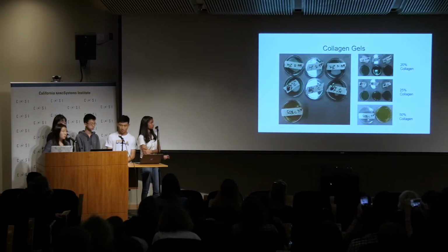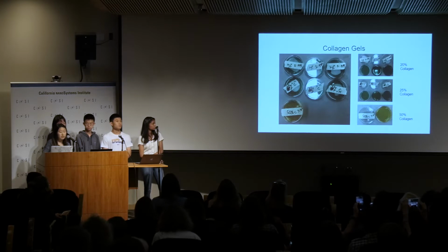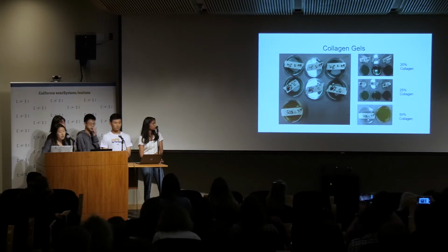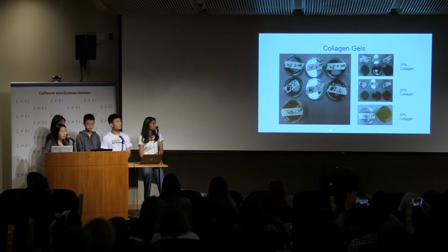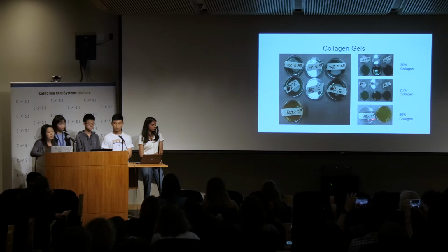So here are pictures of our collagen gels. In the upper right-hand corner, that is our 20% collagen gel. And next we made our 25% collagen gel. And then finally we decided to spike up our collagen by making a 50% collagen in order to try to make a gel, which still did not work in the end.